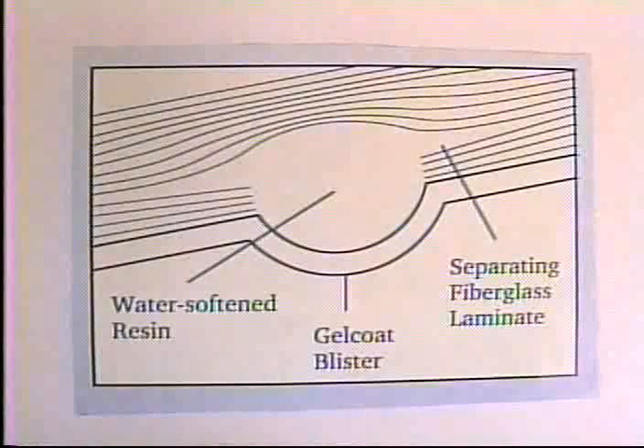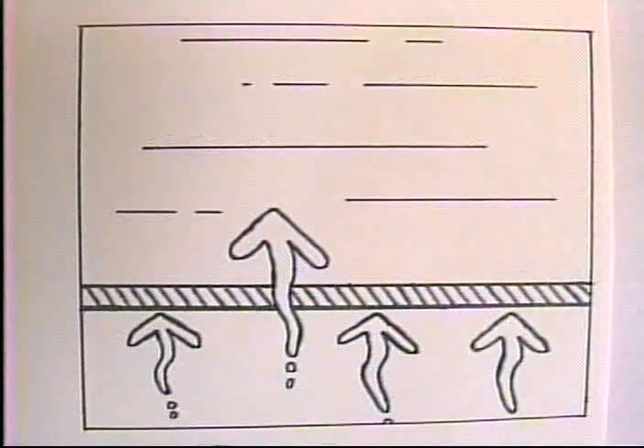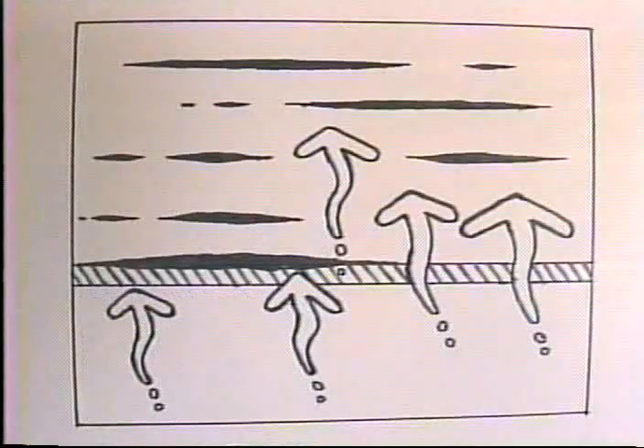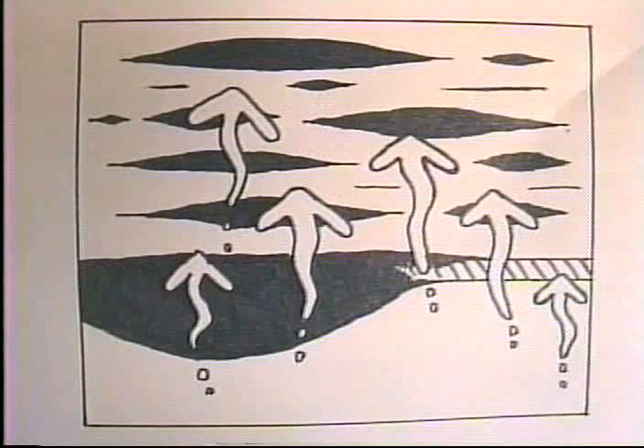About 70% of these vessels have developed hull damage. This is caused when osmosis blisters develop under the gel coat. Here's how it happens. First, water migrates through polyester resins and gel coats, dissolving materials embedded in the laminate. Then even more water is attracted into the voids, diluting solutes in the blister fluid solution. Finally, accumulating fluid builds up hydrostatic pressure between the gel coat and laminate, creating a blister.